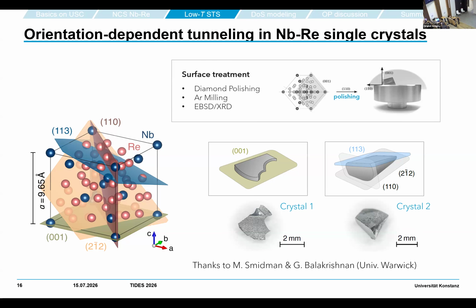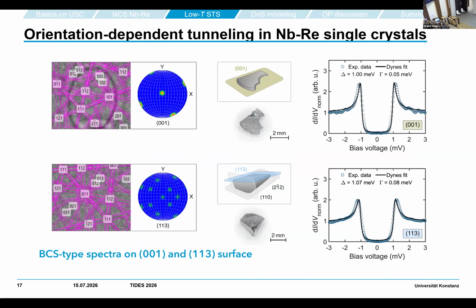First of all, we got crystals with surfaces from the group of Gisa Balakrishnan and Michael Smidman. They had some of these surfaces, 001 and the 113, and the other ones we generated by polishing them at a certain angle. We have chosen these other planes on purpose to probe hypotheses on the order parameter symmetry.